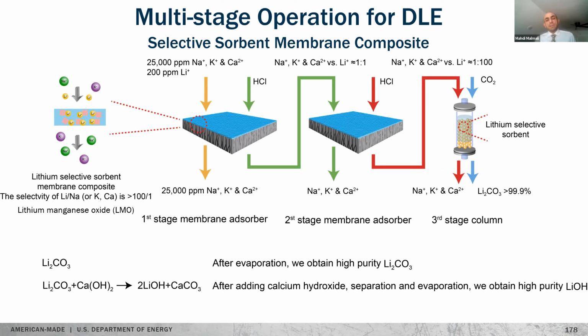In this stage, again, it's being concentrated. Here we'll get, again, a ratio 1/100. And finally, it gets to a fixed bed of the adsorbers. And the product of this is going to be more than 99.9% lithium carbonate. The reason we chose lithium carbonate is because of the lithium prices, and we think that iron-based batteries are now having better market, cheaper prices, so there will be more demand for this.